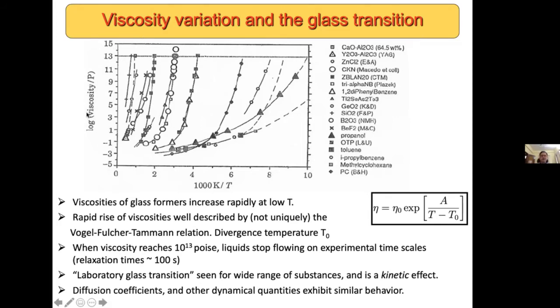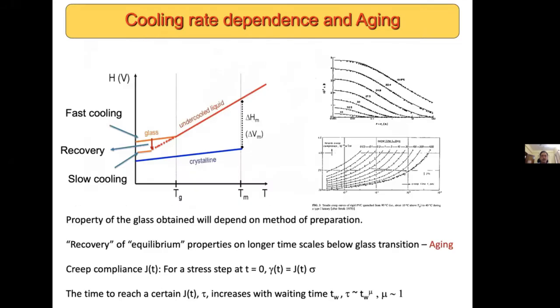And such temperature dependences generally are well described, though not uniquely, by something called the Vogel-Fulcher-Tammann relation, which exhibits a temperature T0 at which the viscosities are expected to diverge by extrapolation. However, one of course never gets to that point. When the viscosity reaches about 10 to the 13 poise, liquids stop flowing on experimental timescales, which corresponds to about 100 seconds. And so what one sees in the laboratory is a kinetic phenomenon where materials start to behave like solids because they're being probed on timescales that are much shorter than their structural relaxation times. Not only the viscosity, but other dynamical quantities exhibit similar behavior. Okay.